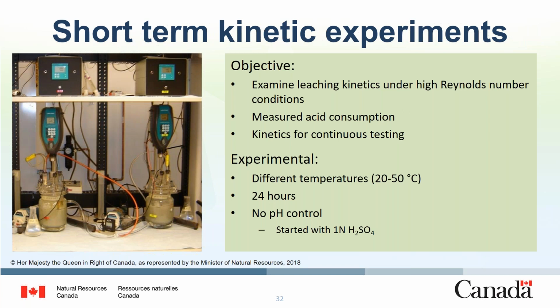So we did some follow-up short-term leaching experiments that were conducted in temperature-controlled reaction vessels with aggressive overhead stirring. The fly ash sample was leached with 1 normal sulfuric acid, 20% pulp density, at 4 different temperatures with a couple of replicates at the center point. These short-term kinetic experiments are essential to determine the scale-up factors and establishing experimental parameters for testing during the continuous operation we hope will be later on this year and early next year.